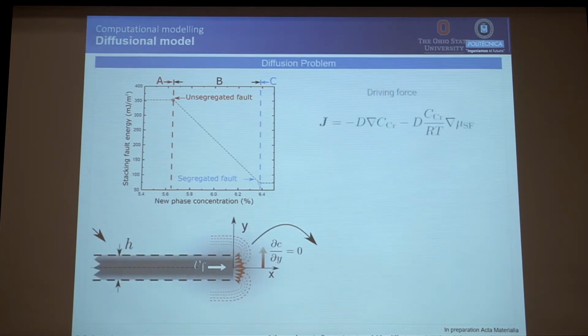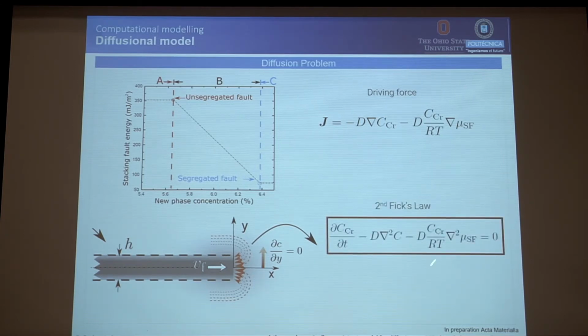So there is a driving force, we need to solve the diffusion field, and there is a driving force that is not coming from the standard Fick's law, so it's not just the gradient of concentration, but it's also the gradient of chemical potential from the stacking fault energy that you can see here. So our diffusion equation is enhanced by this term that we need to take into account in the solver.